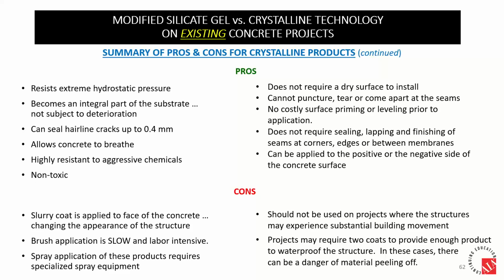A couple of cons are it will change the surface. It's a slow, labor-intensive process. And if you do go with the spray method, that is very specialized equipment. Should not be used on structures with significant movement. And it does require a couple of coats, in most cases at least 2 coats to use this.